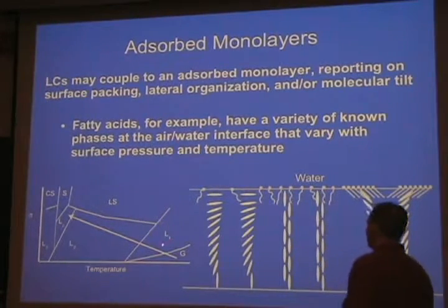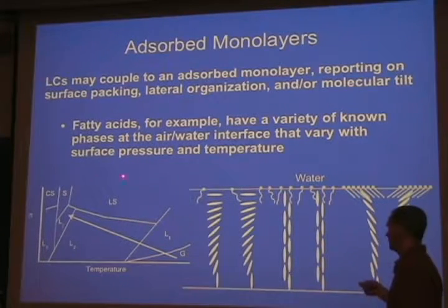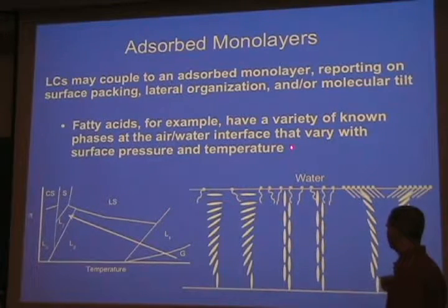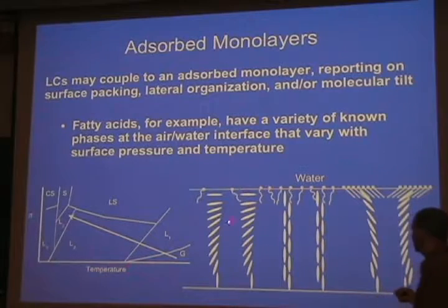But we found that one could also adsorb monolayers of these same fatty acids at the nematic-water interface, and depending on the concentration of the fatty acid at the interfacial layer and the way the molecules are organized, we got different types of anchoring. So, for example, if the fatty acid molecules, these surfactants, were very dilute at the interface, then it was essentially as if they weren't there, and the liquid crystal molecules adopted a planar anchoring.